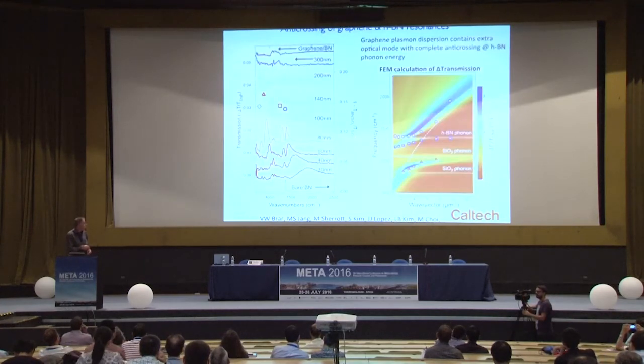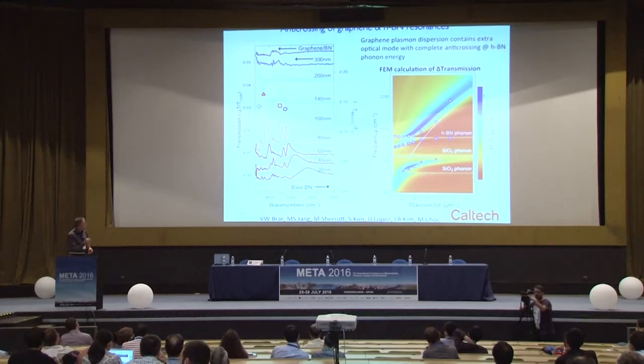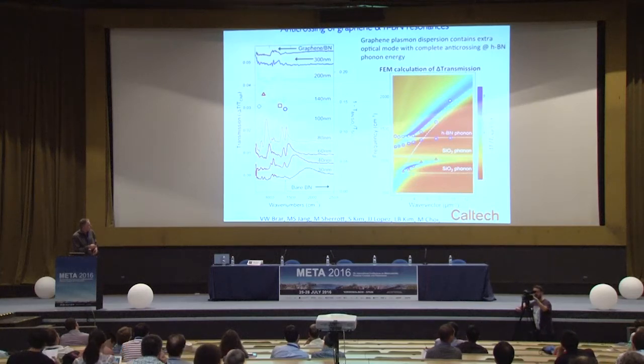And the hybridization of the phonon polariton with the plasmon leads to a hybridized interaction as we change the carrier density in graphene and we tune the graphene plasmon resonance. It crosses the phonon polariton line in boron nitride. This is shown here for a bulk boron nitride, showing the position of the phonon polariton peak. And you can see here there's an apparent anti-crossing behavior, a splitting of the graphene plasmon resonance as it hybridizes with the phonon polariton. And if we work with electric dipole resonators of different sizes, we can actually map out the entire dispersion relations here and see this nice anti-crossing manifest as a coupling between the phonon polariton and the graphene plasmon.